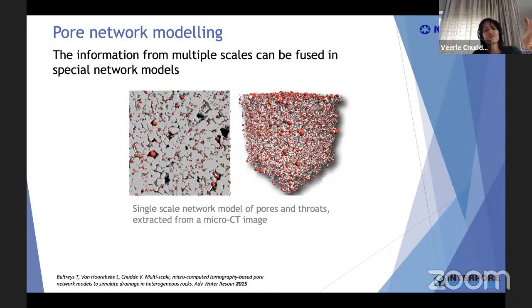So we use the CT data that we used to look at the processes also as input for pore network models. So you have your CT image, for instance here on the left, and then we make a representation of the pore bodies with red dots and the pore throats with cylinders, in order to represent the pore network in a simplified way.